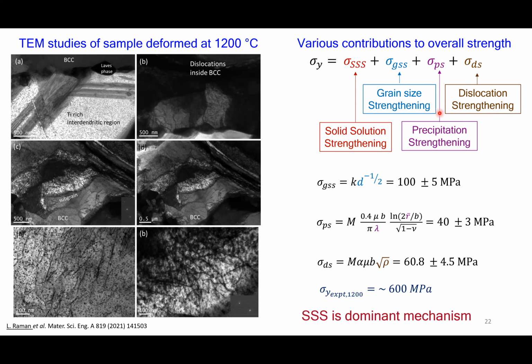Okay, and so you did not actually calculate the solid solution strengthening, right? It was just taken as a difference of the expected strength. Yeah, we did calculate the solid solution strengthening, but I did not cover it in the PPT. Maybe you can check this manuscript, so that will help more. So you take into account the amount of solid solution available and then the contribution of each of the elements? Yes, the composition of each element and how the individual physical properties, such as the shear modulus or the Poisson's ratio, affect it. How much is available in solid solution? How do you take that into account? Because you might have given an initial composition, but only so much is available as solid solution. How do you find that?